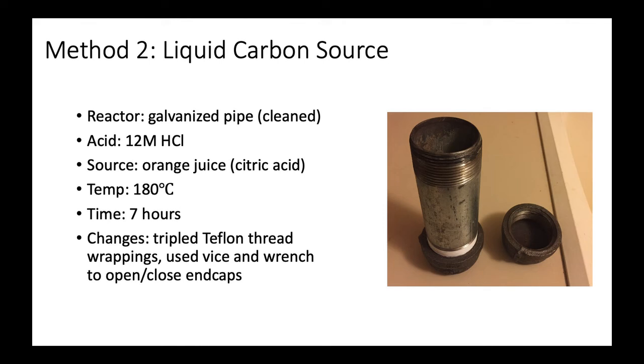When I reran this with the liquid carbon source, I made some adjustments to the procedure to avoid some of the leaking problems. I tripled the Teflon tape layers and used a vise and wrench to make sure that nothing could leak out. Using orange juice, which contains citric acid, as a liquid carbon source, I repeated the same procedure.